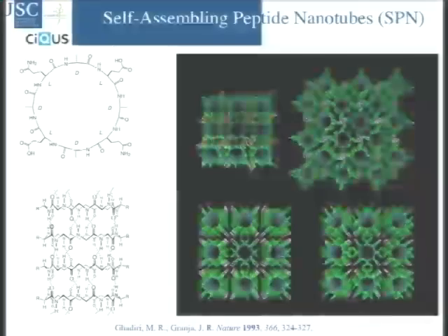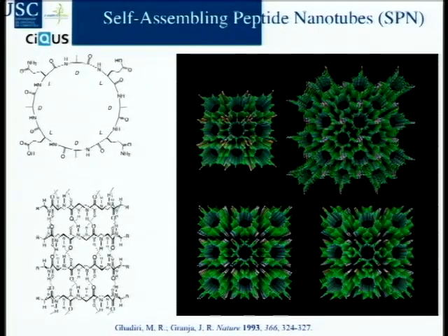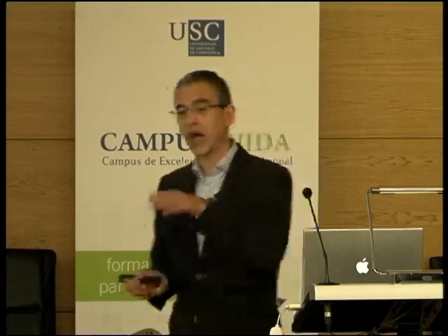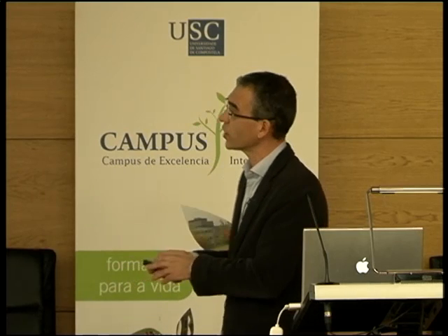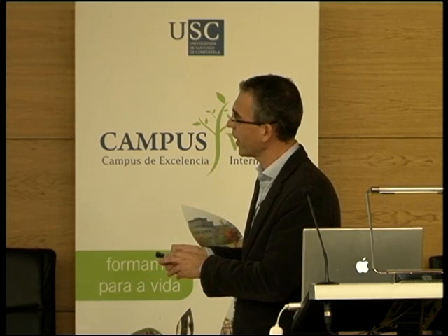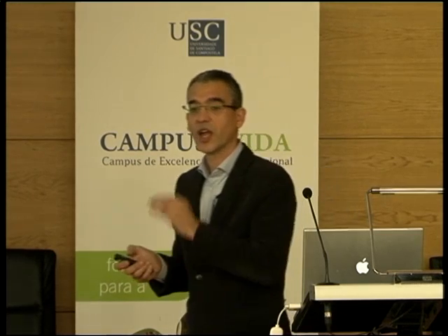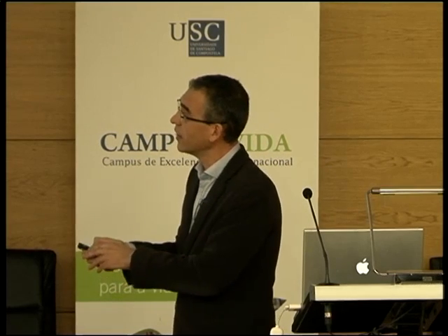Let me show you a different kind of nanotubes that are related to biomaterials. They are made by peptides with a specific sequence that are able to adopt a flat conformation in which the carbonyl and NH groups allow the formation of hydrogen bond interactions, so they stack on top of each other. Interestingly, in this type of structure the diameter of the nanotube can be precisely controlled by the size of